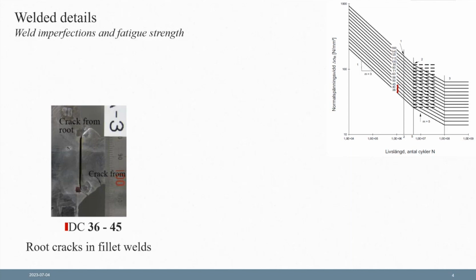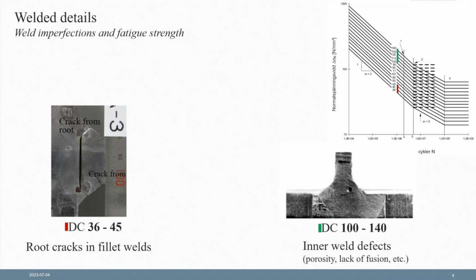One way of categorizing these welded details is to look at details with very low fatigue strength, the lowest curves, and these refer to a mode of cracking which we call root cracks. These are cracks that initiate and grow through the weld itself. These kinds of fatigue cracks have very low fatigue strength, but they can be mitigated or avoided by increasing the weld throat thickness, having bigger welds, or prescribing partial penetration or full penetration welds in design.